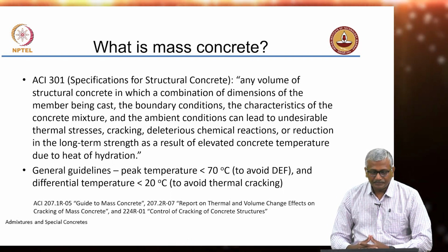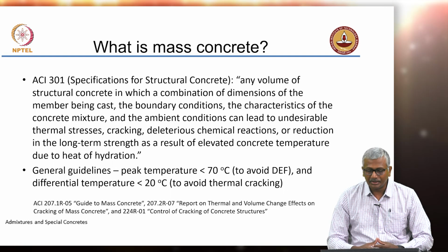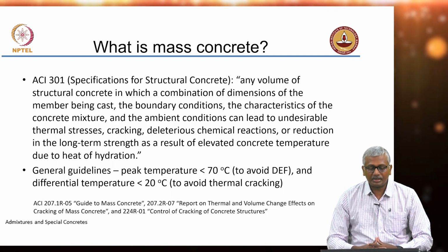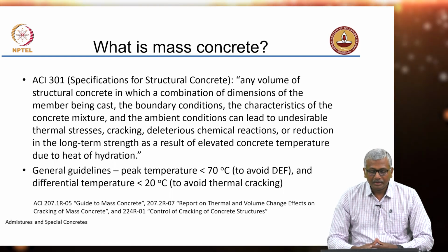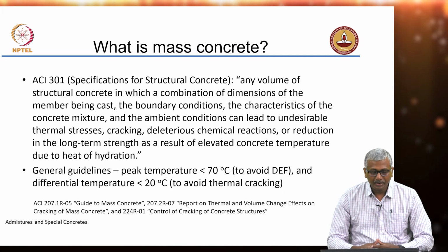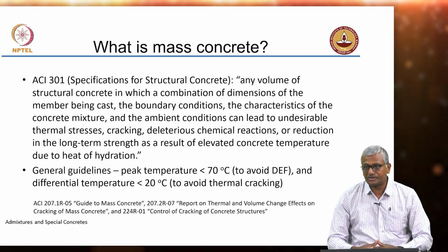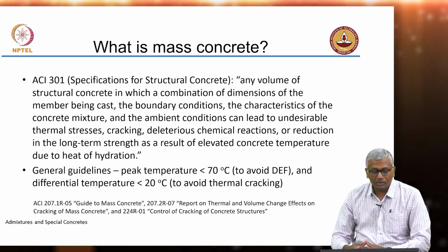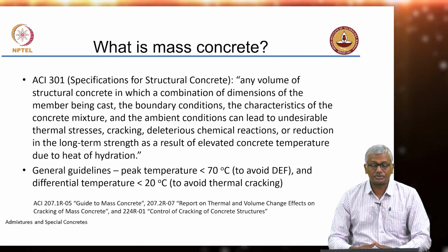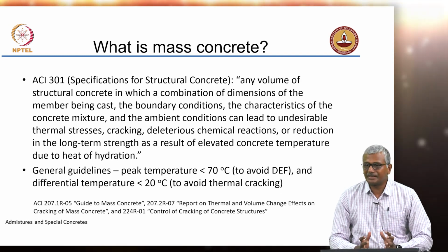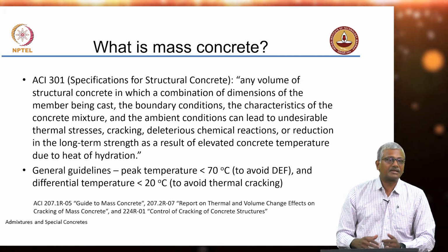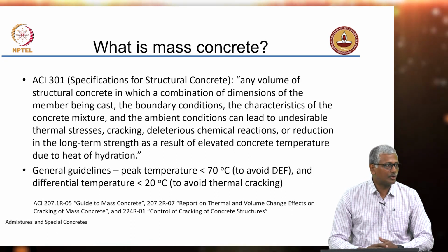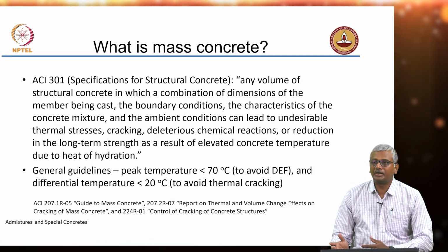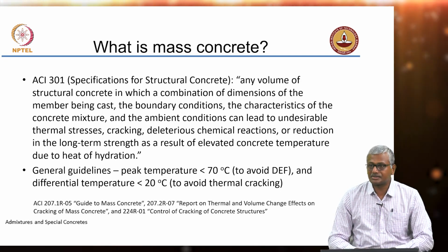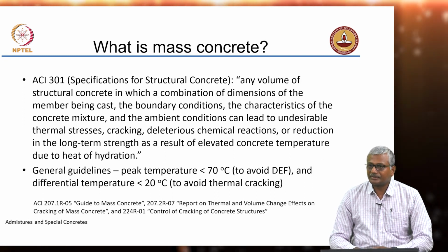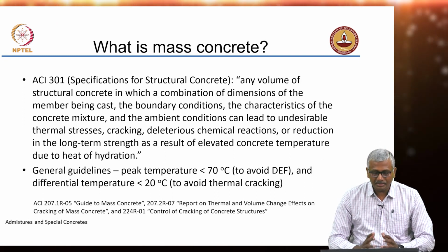As per ACI 301, which is basically the specifications for structural concrete, it defines mass concrete as any volume of structural concrete in which a combination of dimensions of the member being cast, the boundary conditions, the characteristics of the concrete mixture and the ambient conditions can lead to undesirable thermal stresses, cracking, deleterious chemical reactions or reduction in the long term strength as a result of elevated concrete temperature due to heat of hydration. So, very clearly it specifies that it is not just one reason, but a multitude of reasons that can together work to create this issue of either long term strength and durability getting reduced or cracking getting created in the system.